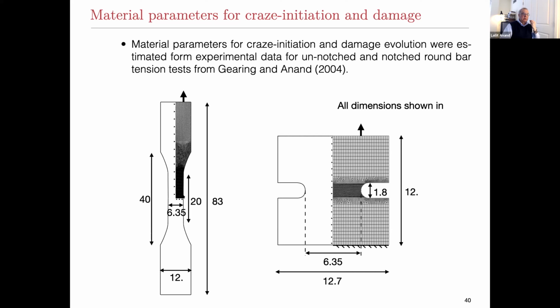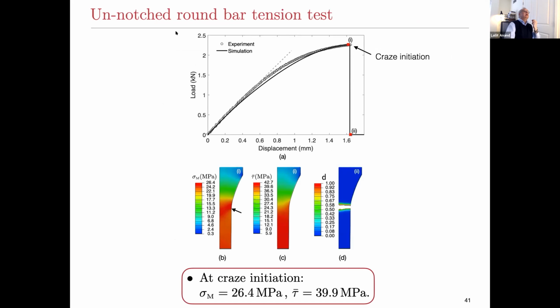So here, this is a smooth bar tension test in PMMA. This is a notched bar tension test. From here, you can try to estimate, as I'll show you from these experimental data, what the craze initiation condition is. So if you do a round bar tension test on PMMA, you see this load displacement curve. It's not linear. People treat PMMA as a brittle material with linear elastic response. It is not. So you get this nonlinearity, and this is the linear response. These are the material parameters that I showed you before, from the plasticity part, so the elastic plastic response. And then from this point, you can estimate by doing the numerical simulation what the mean normal stress is and what the equivalent shear stress is at which craze starts.